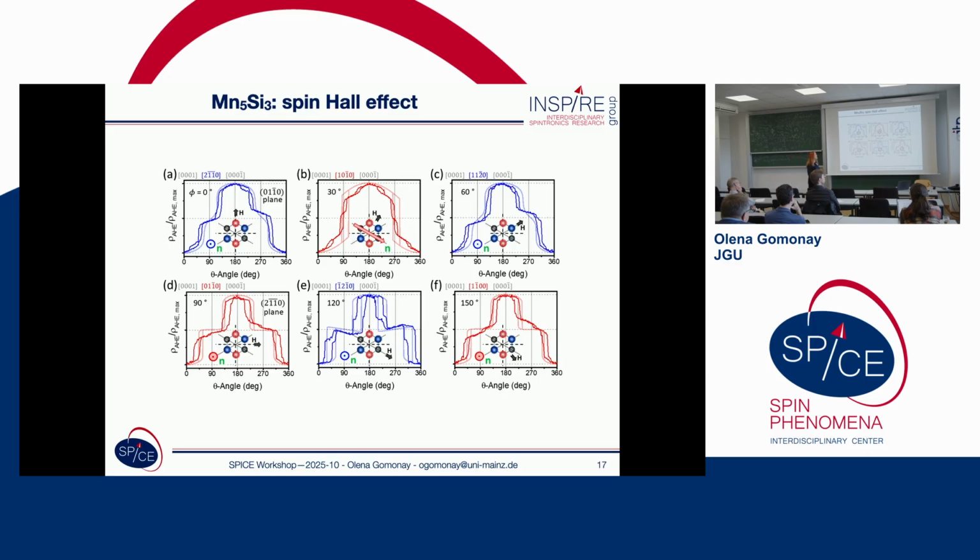So now I return back to this experimental part. So, smoking guns. What specific pictures among all these do we see? So we see this curve, which is very different from the others, because all these curves have a shoulder at 90 degrees and 270 degrees, and this does not. So I would say that all these curves show that the system undergoes transitions through at least 3 states, here, here, and here. And in this case, we have transition only between 2 states, which are separated by 180 degrees. So it was smoking gun number 1.